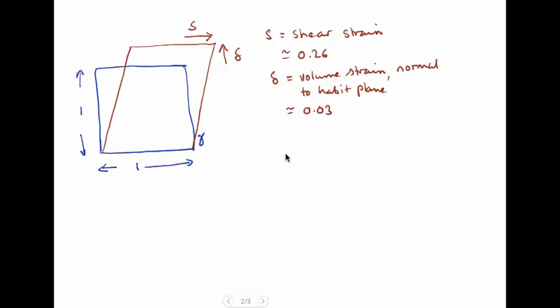These are very large deformations. A typical elastic strain when we pull a piece of steel to a stress of 200 megapascals has a strain of only 10 to the minus 3. Therefore, there will be very large strain energy terms when martensite forms within a material because these large displacements are pushing against the other crystals surrounding it.